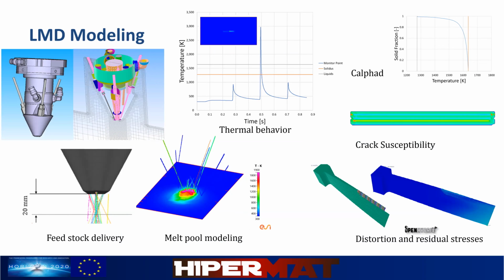So in total, we have a process chain, very much like ICME, where one model is focused on a certain length and time scale, providing certain information, which we adopt in the next model, focusing on yet a different aspect of the process. We have talked in detail about feedstock delivery, melt pools, thermodynamic calculations, crack susceptibility. I did not present any work done yet about distortion and residual stresses, so I captured an example of repairing a steam turbine blade, looking at deposition strategies, taking the properties predicted and determining what kind of stresses and distortions are to be expected. On the next slide, we have a summary.